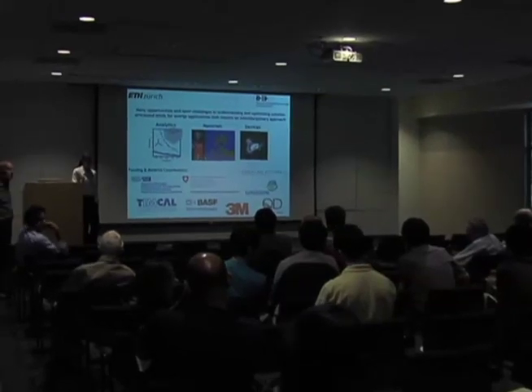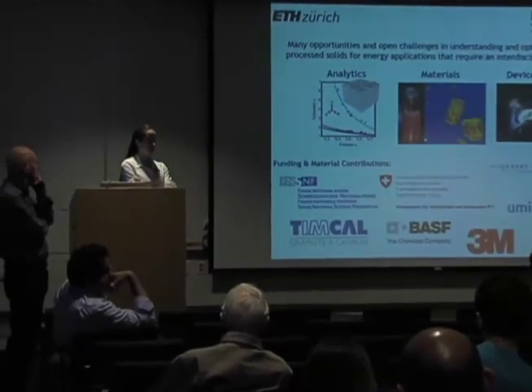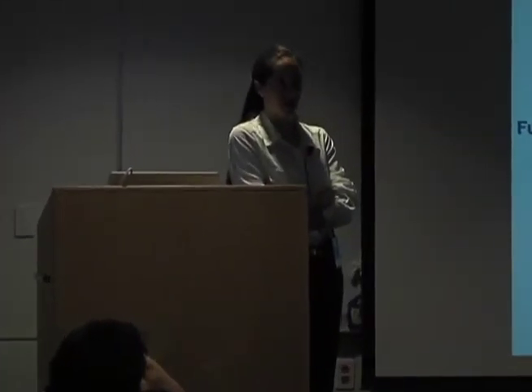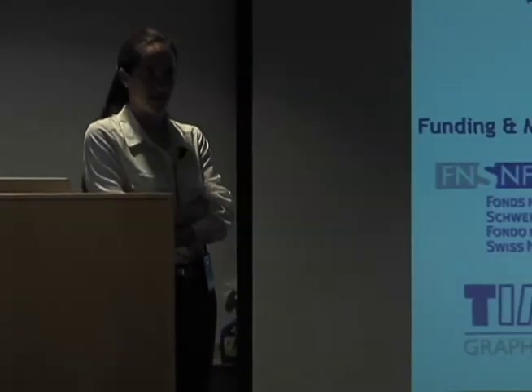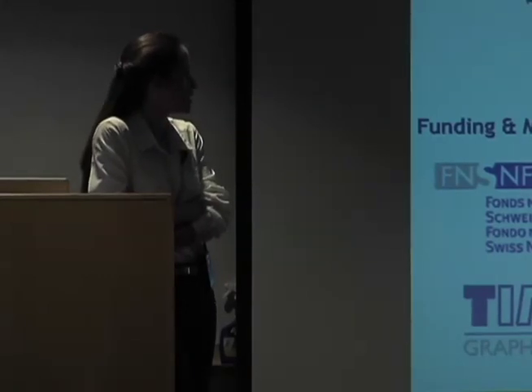So the different colors, the red and the green, you mean? Okay. So I think that's one of the major challenges. One of the issues in designing quantum dots that still hasn't been achieved is understanding of the thermal stability. It's not necessarily a thermal degradation process, simply a thermal reversibility. It's known that as quantum dots heat up, they lose quantum efficiency. And of course, this becomes a major challenge in a lighting application where you have a high intensity gallium nitride source.